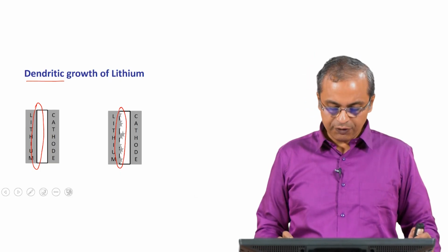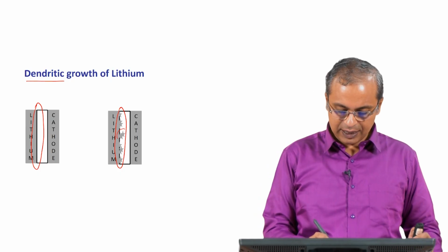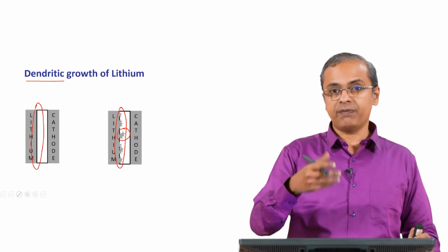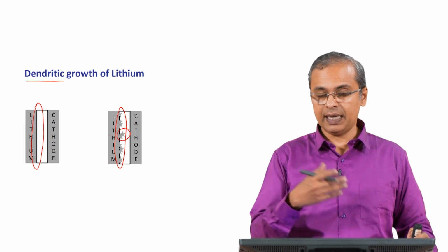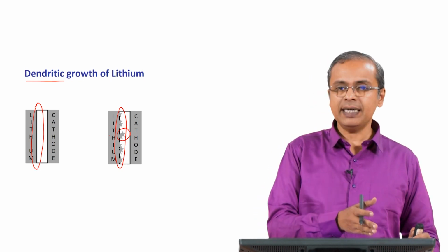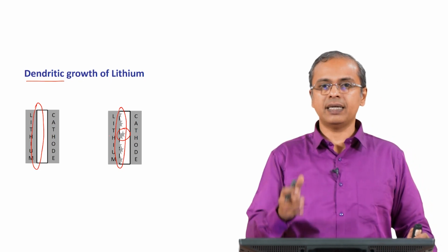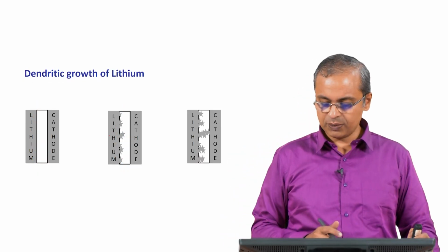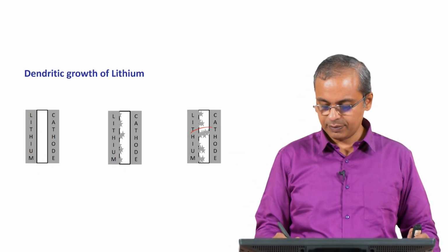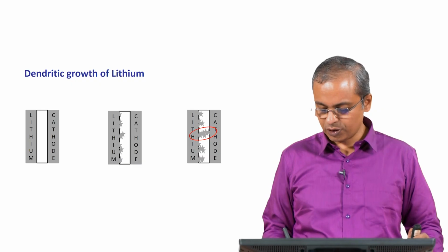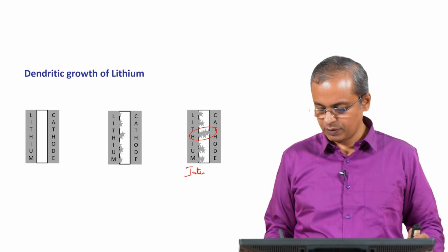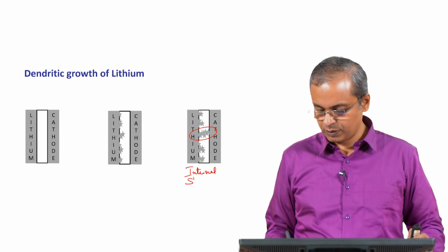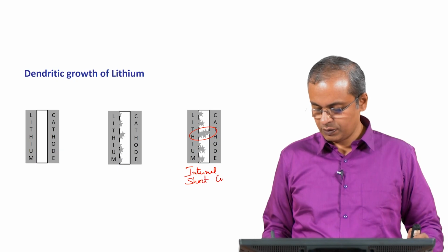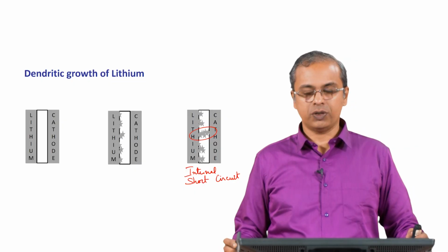This is a nice uniform surface interface, a flat surface which has now become a pointy surface which is highly uneven. So, if you continue this, you can see now for example, this is a little bit ahead, this will keep growing faster with progressive cycling every cycle. Initially it is okay, first cycle, second cycle, third cycle, as you continue you will eventually reach a situation where it looks like this. You have an internal short circuit.